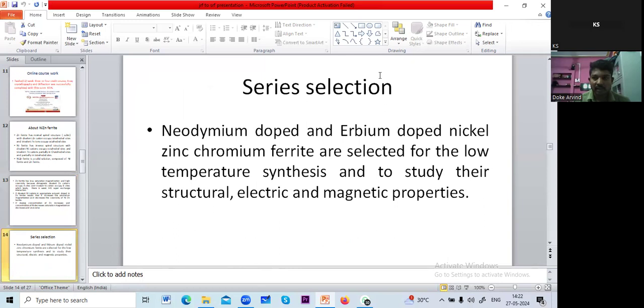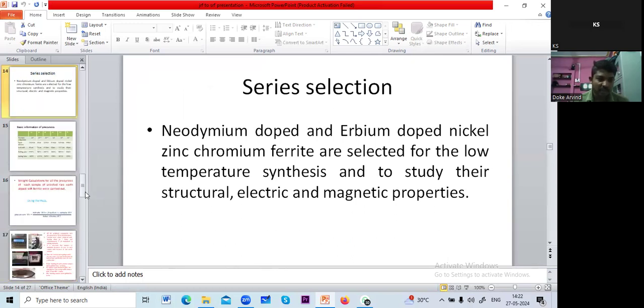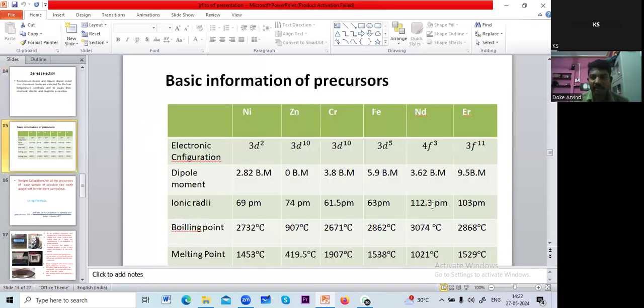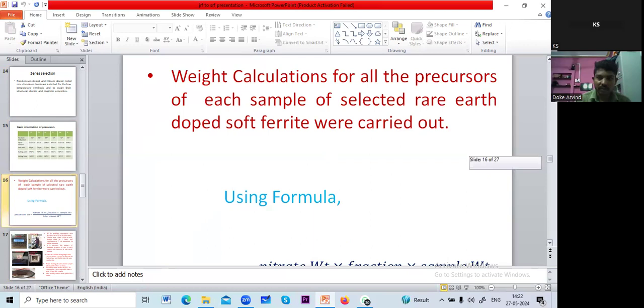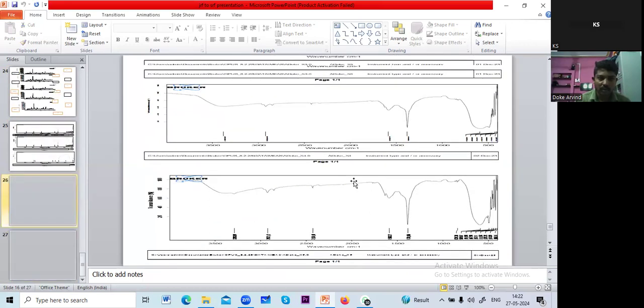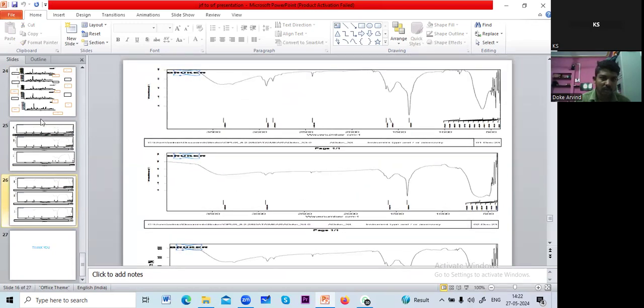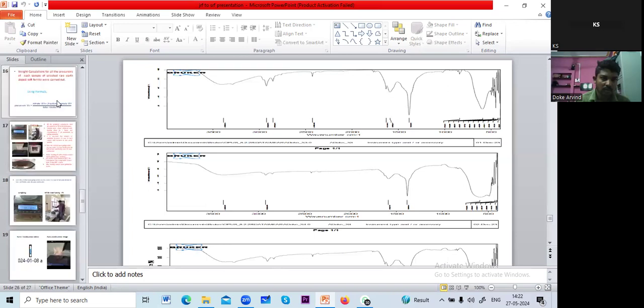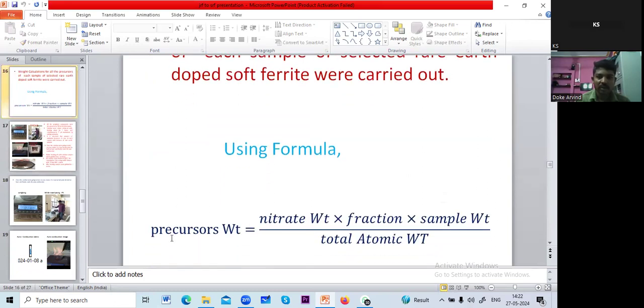After that, I selected the series for the synthesis of my sample. That is neodymium soft ferrite and erbium soft ferrite. There is some basic information about the elements that I had taken for the synthesis to make the nanoparticles. Using this formula, I calculate the sample weight for the synthesis.